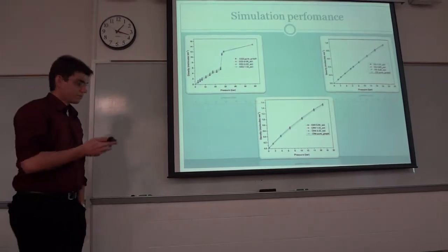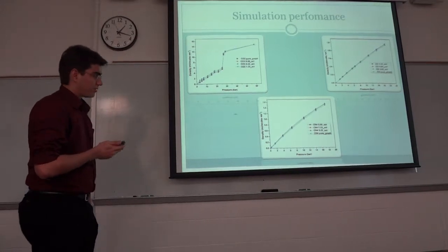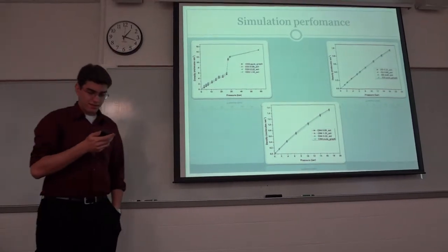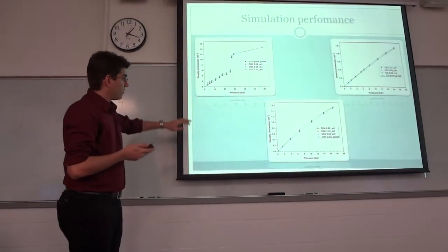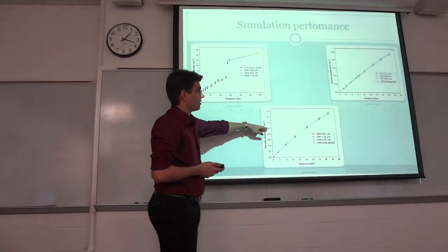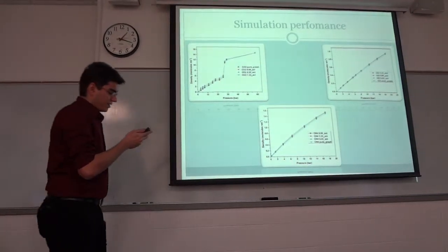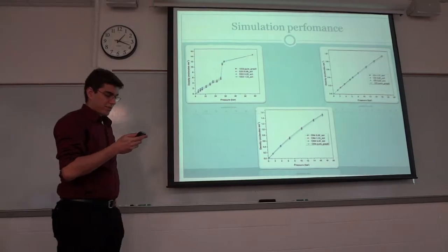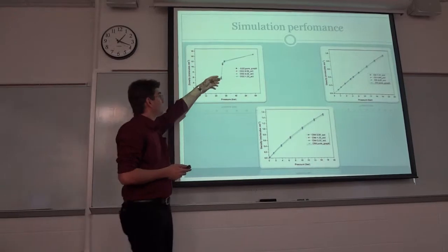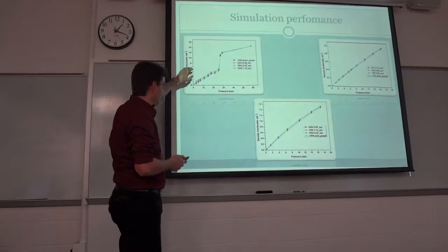Now we have the simulated absorption isotherms at 298 Kelvin. Looking at the graphics, we can observe that the amount of gas absorbed follows the order: CO2 absorbed more than CH4, which absorbed more than CO, which is in agreement with a previous study made by the same people. This part of the isotherm is called the capillary condensation phenomenon.